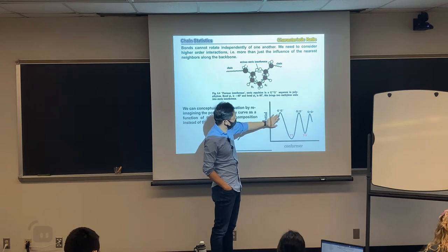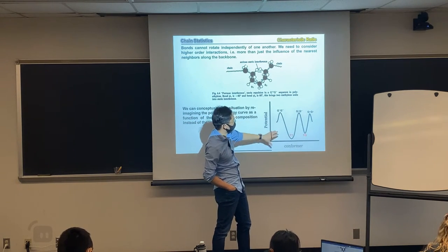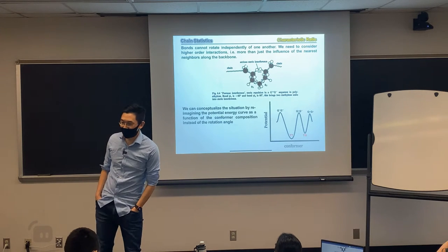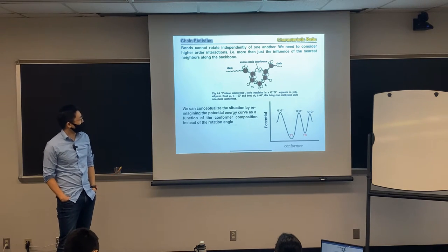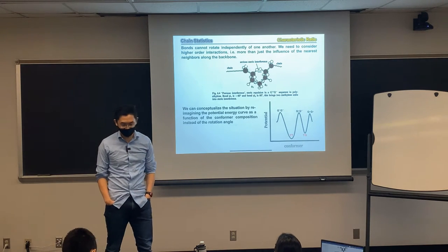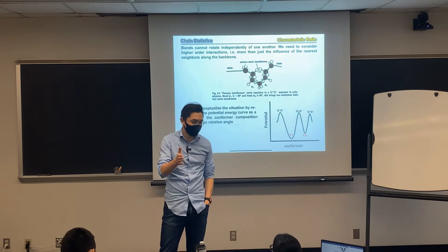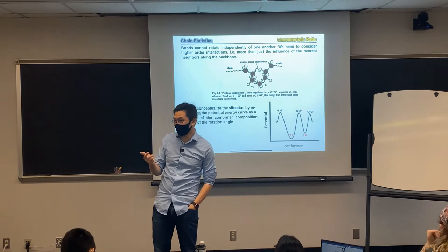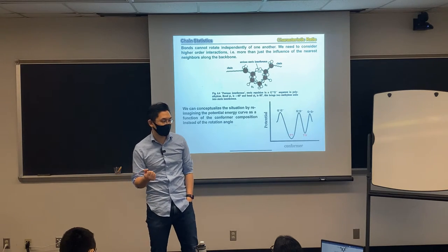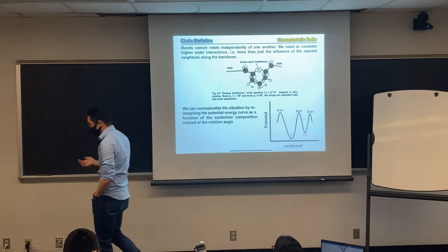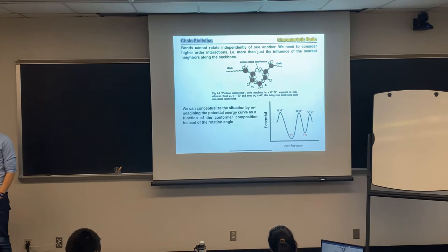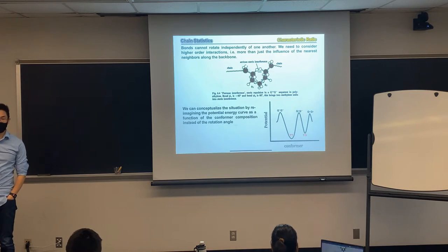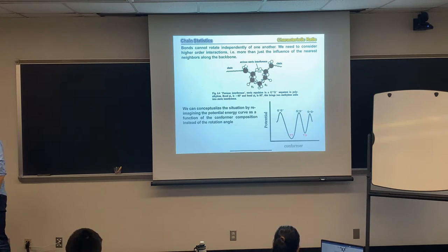You can see this would impact the rotation energy potential. It's no longer going to be that beautiful symmetric gauche trans cis model we just described. All right? So the most accurate way in polymer is still measuring it. We're going to talk in October about how we measure them. There are several techniques we can use. Light scattering is one of them. And there's also a technique using osmotic pressure in polymer solution to look at how rigid polymers are. But for now, you just need to know our model is still a little bit limited, just because even the three models, free joint chain, free rotation, and rotational isomer chain, have certain limitations.